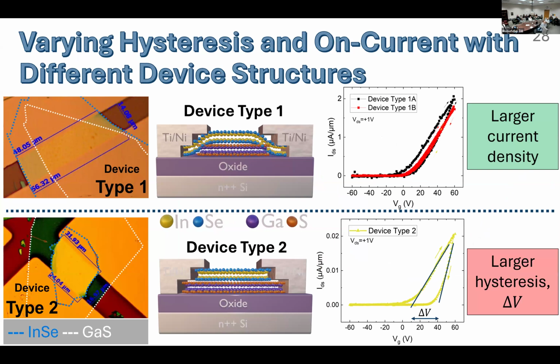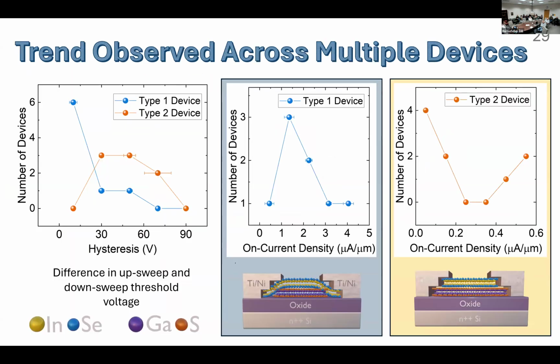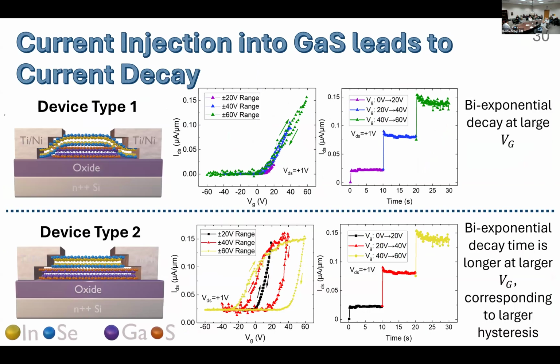Okay, so going forward, we can explore the other two different device configurations, and we notice two distinct behaviors. For device type 1, we experience a larger current density and a reduction in the hysteresis, whereas in device type 2, we see a larger hysteresis and a decrease in the current density. This trend is observed across multiple devices, so it's not that we're just seeing a couple and leading to these conclusions. So what we decided to do is conduct time-dependent conductance measurements to see where this current is flowing in each device type.